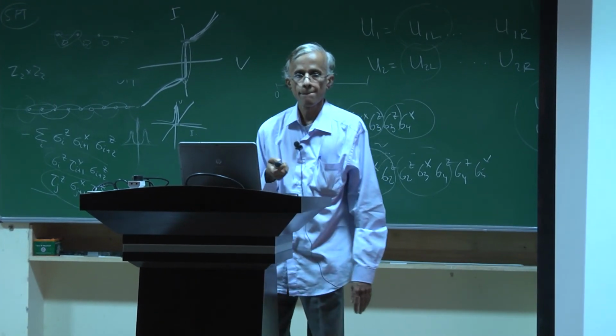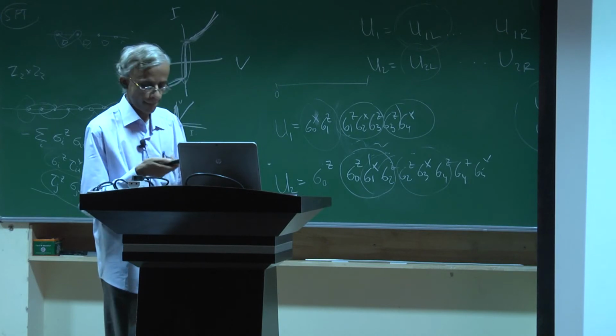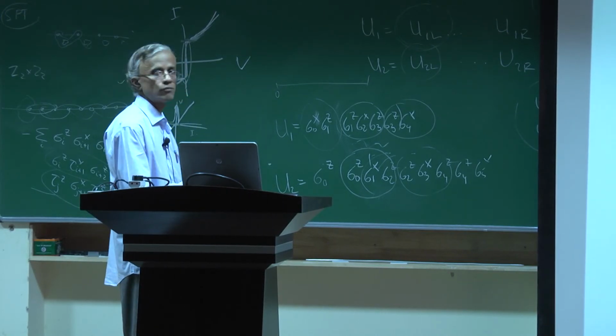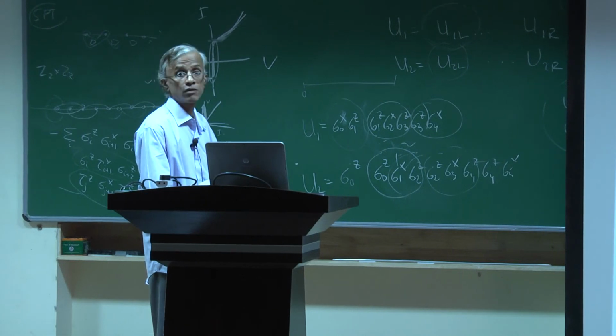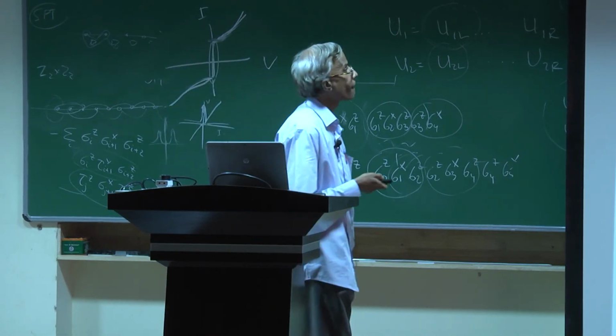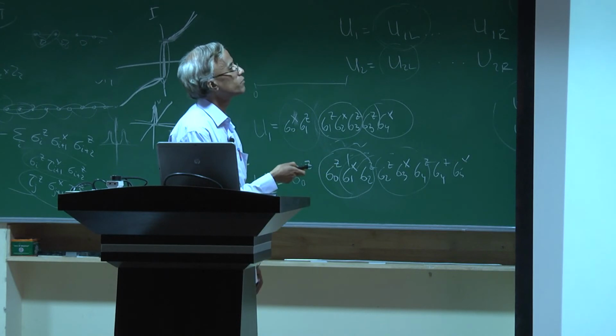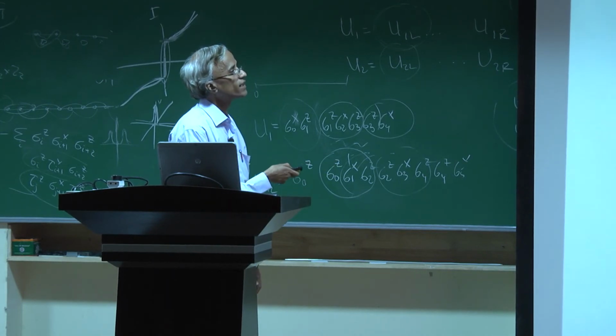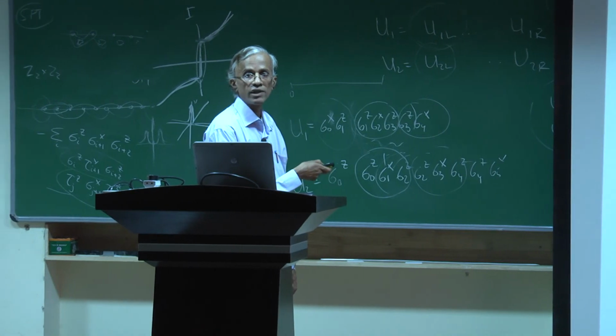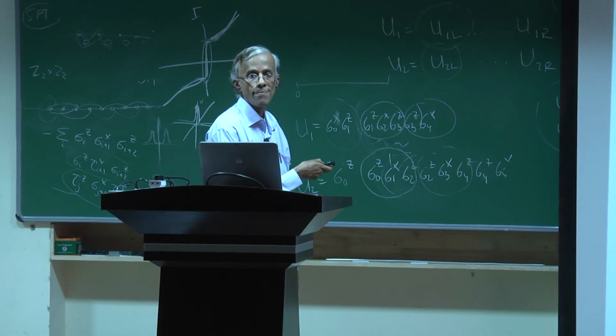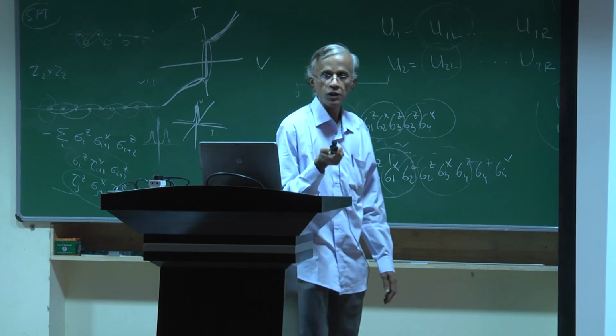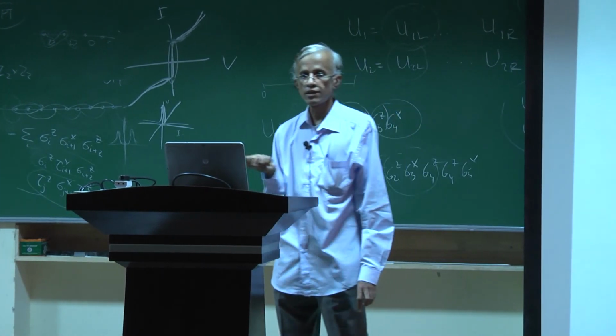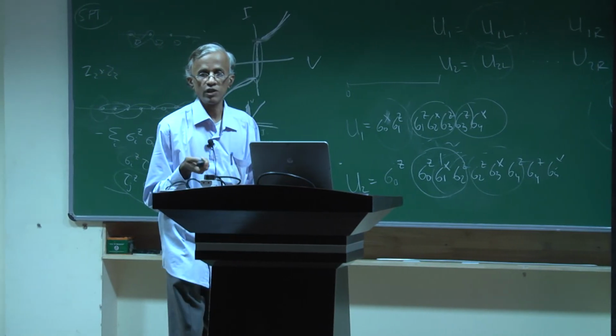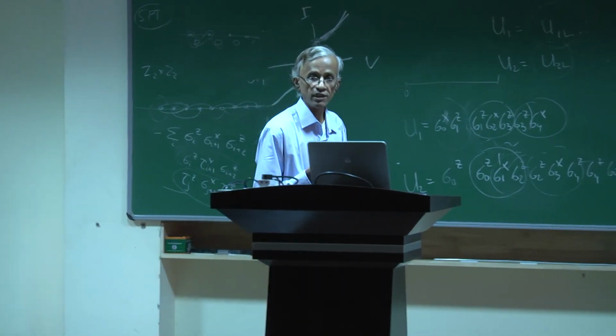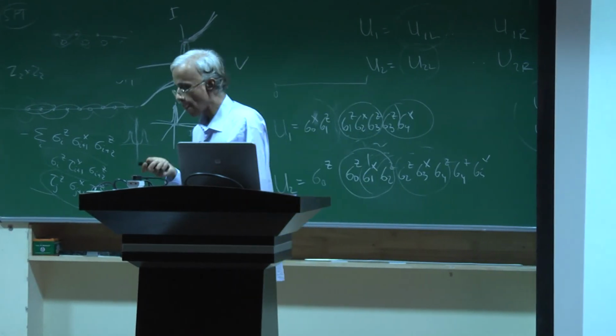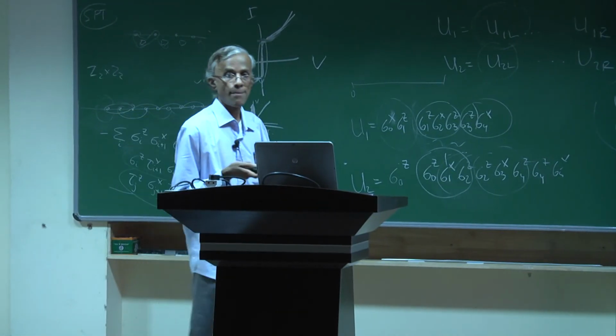What breaks the symmetry between the XZ orbital and the YZ orbital? It started with the residual interaction. Because if you rewrite it, basically you can see that the XZ is lowered by a small amount relative to YZ. That immediately induces ferroorbital order. And since the orbitals have a directionality, that also induces a spontaneous breaking of the four-fold rotational symmetry of the square lattice.